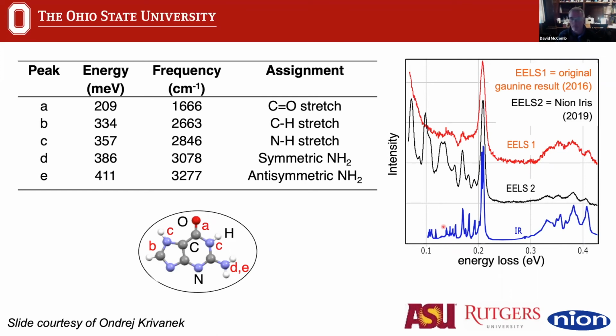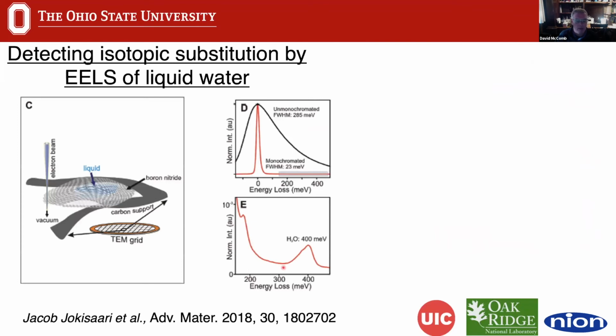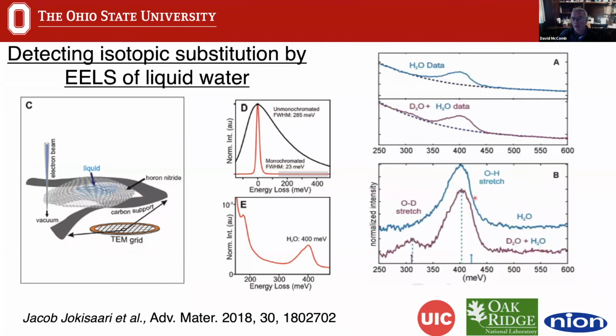This really is incredibly powerful as we start to think about how we might apply this. And a really nice example of how you can do this is done by two groups. One with Robert Klie's group, where they were looking at actually liquid water. But what they did was they collected the very low energy spectrum from water and also from deuterated water. And you could see that in the case of when the D2O was present, you could see this additional stretch, which is the oxygen-deuterium stretch, and this is the OH stretch. And they showed that very nicely, published that back in 2018.